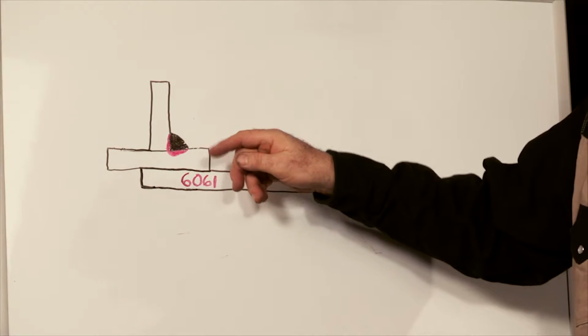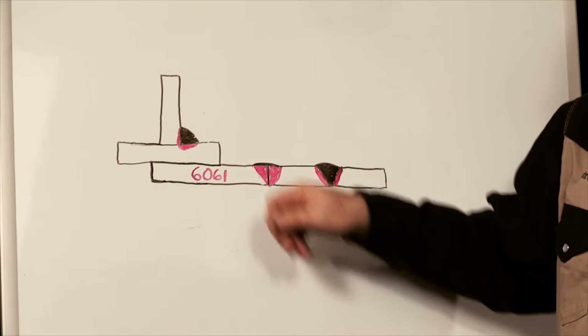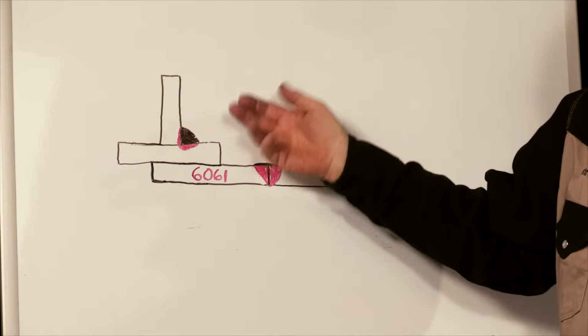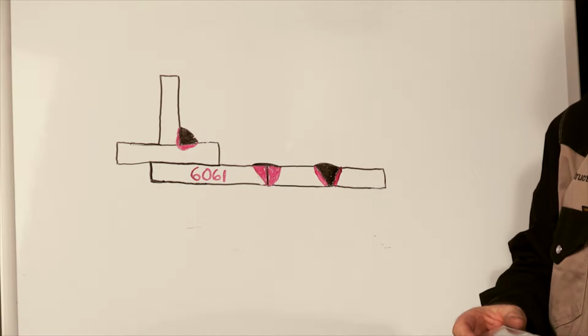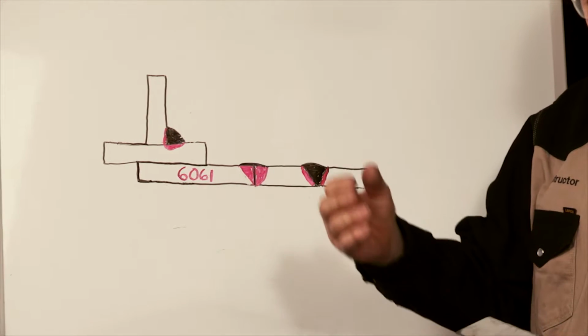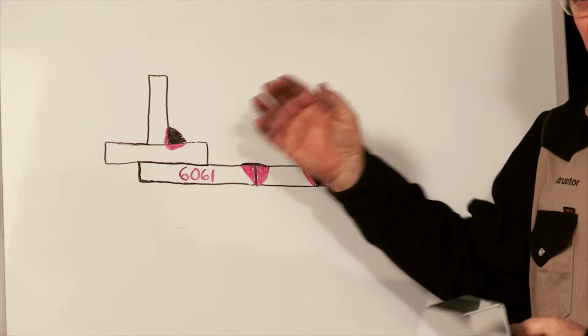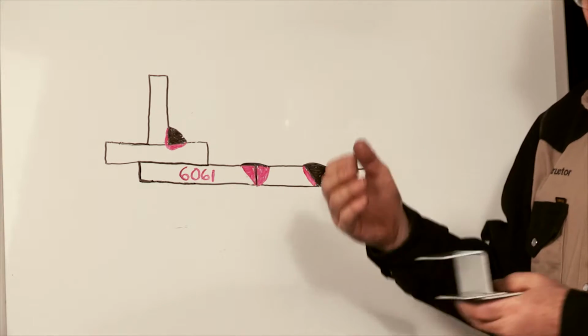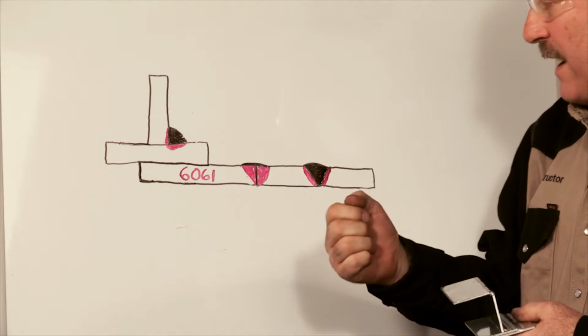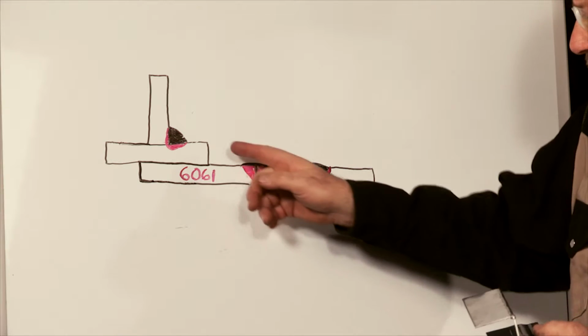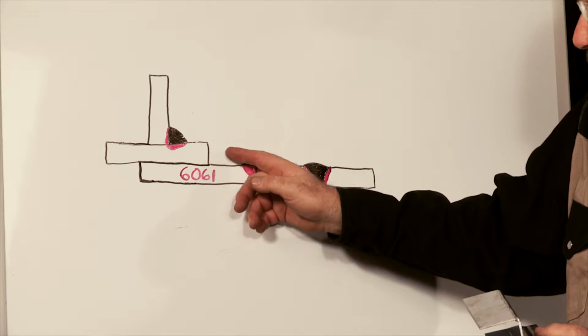And of course, in order to get fusion, we also have to melt some of that base metal. Well, if you look at that picture, you can see there's quite a bit more filler metal than there is base metal. And that weld will not be prone to cracking. The 4 series filler metal, or 5 series filler metal for that matter, will change the chemistry of that weld deposit so we don't get a crack. When we do a lap weld, same thing, it's a fillet weld, but we have to be careful with lap welds that we add plenty of filler.